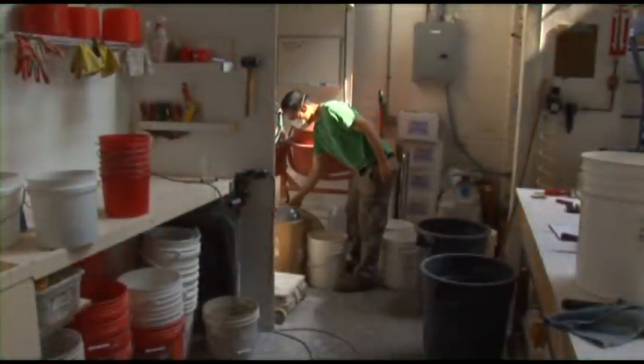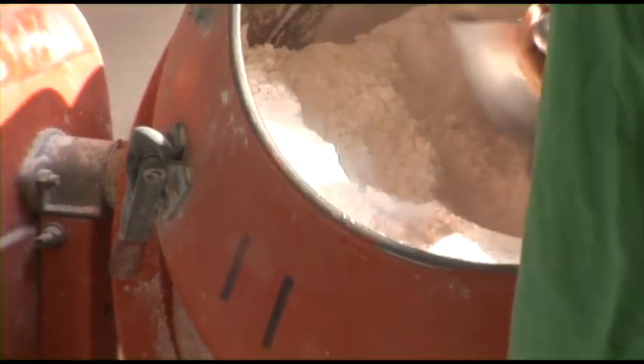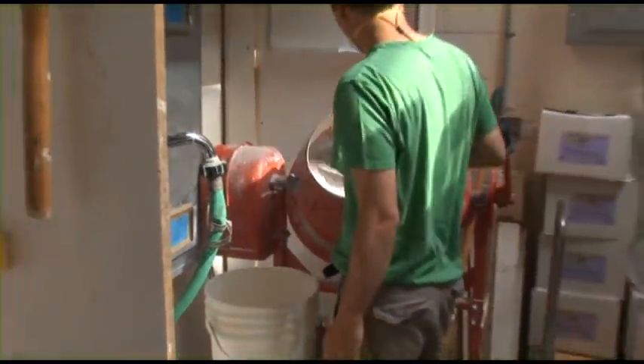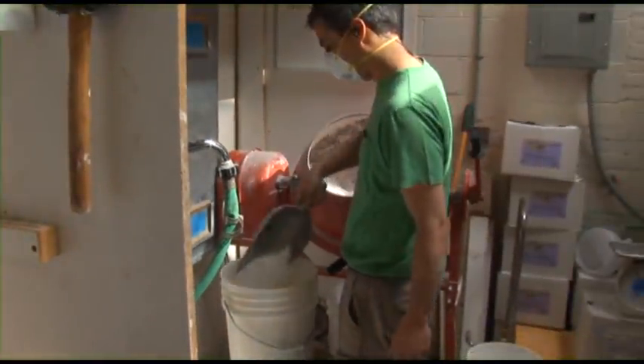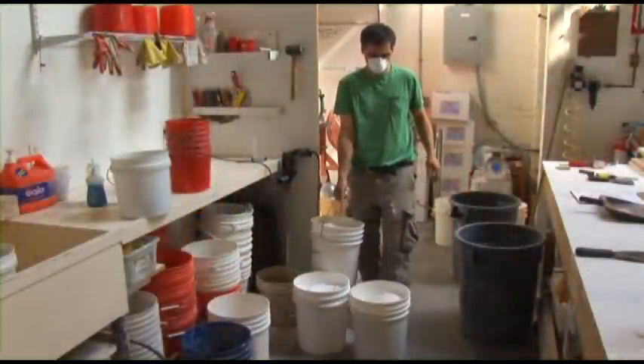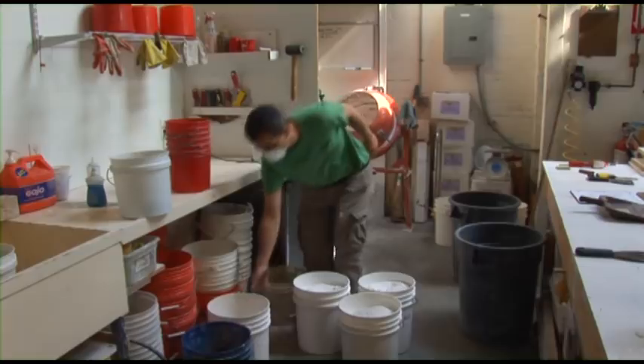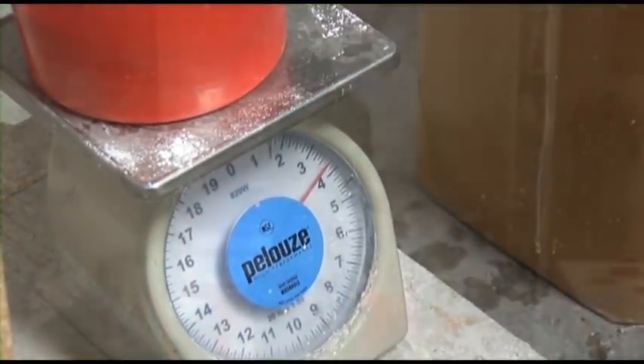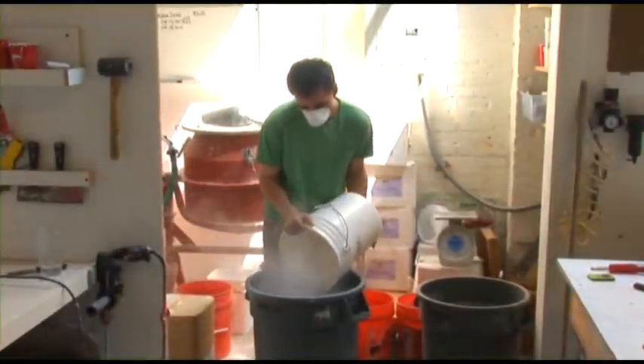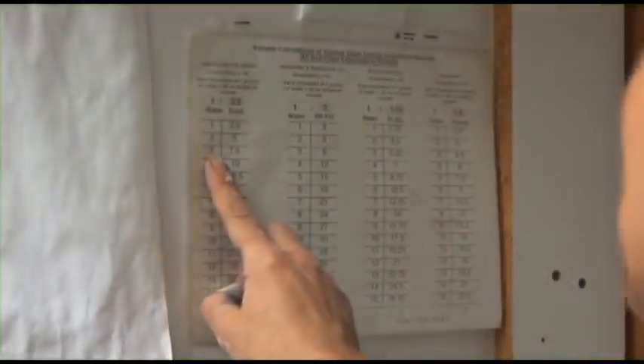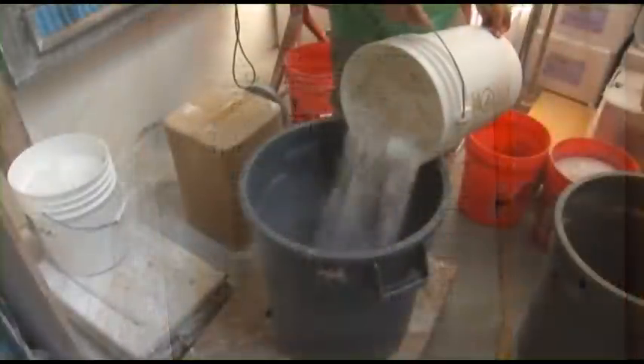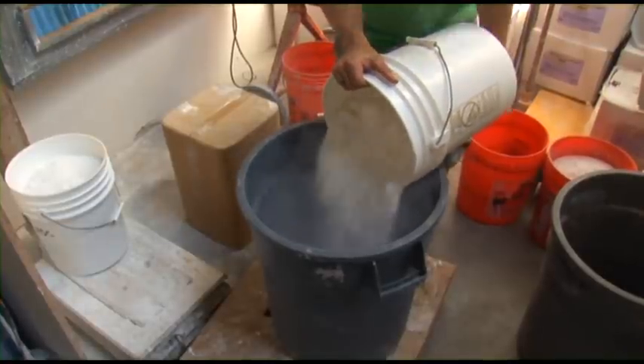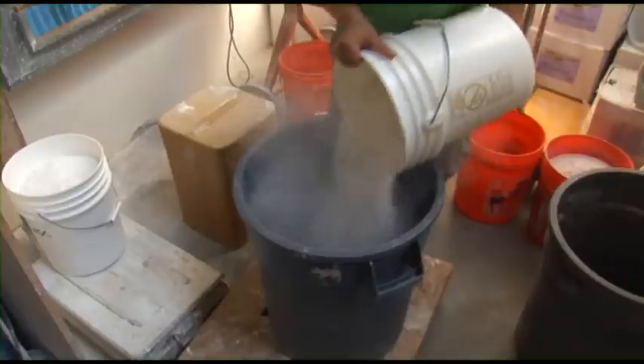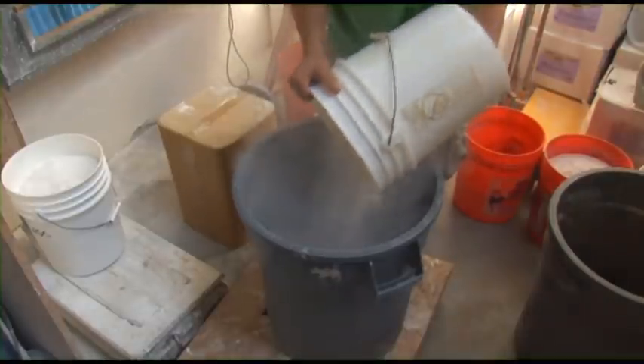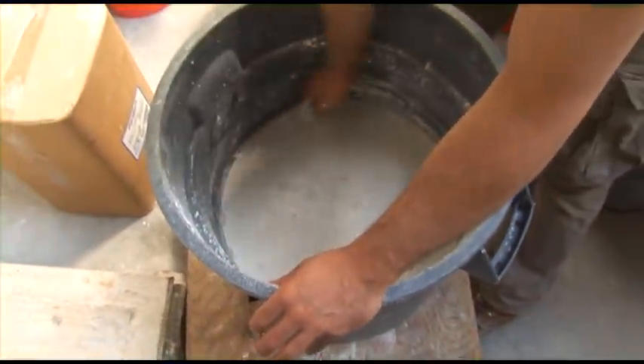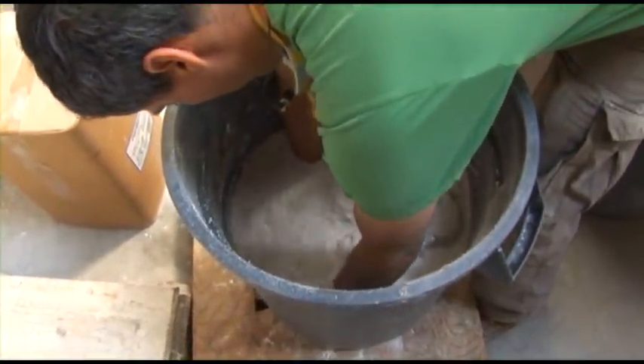When I first started casting glass into plaster molds, there was some knowledge, but it was kind of loose. And it resulted in lots of failures over time. And one thing I discovered in my first few years, that if you pay attention to the water to plaster ratio by weight and mix it properly, your percentage of success goes way up. Very early on, I started setting charts up and standardizing everything. We know by experience and good record keeping how much plaster material we have to mix up to make this mold. And that's 2 big garbage cans of plaster that Jim will have weighed out, ready to go, plus some backup plaster in case I feel like I need more.